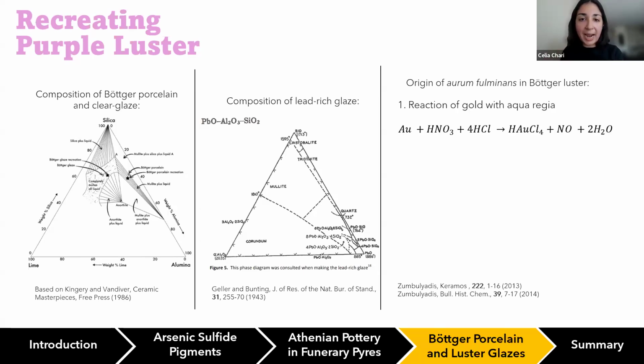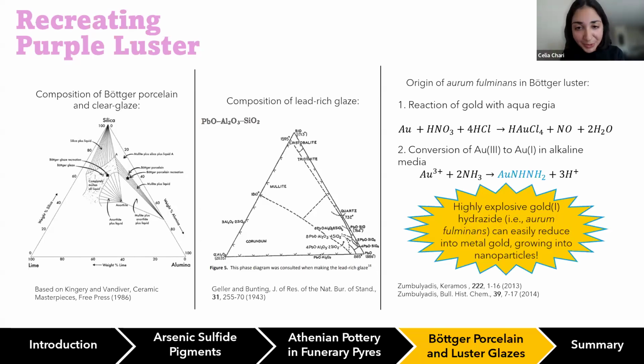So it starts off by reacting gold leaf with aqua regia to form these gold salts. These salts are then converted into the highly explosive gold hydrazide that easily reduces into metal gold and can grow into nanoparticles. Gold hydrazide is very sensitive to air and to moisture. So it's thought that this is mixed intimately with the frit and then applied directly onto the surface just to minimize the contact of these salts with air.